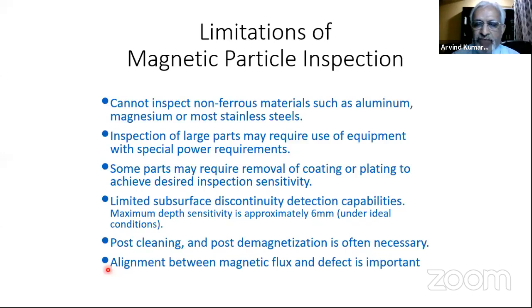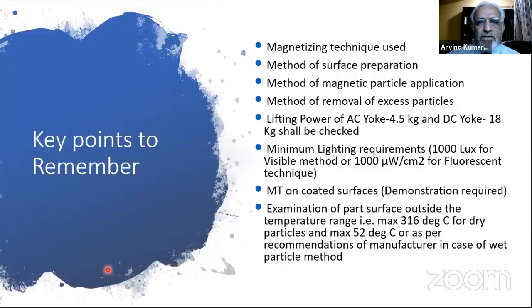Alignment between the magnetic flux and the defect is important. That means how you magnetize: if you are looking for a transverse defect, then you have to introduce a longitudinal field and vice versa. Again, what important things are there in this? What is my magnetizing technique? How do I prepare my surface? These are all essential things which we should follow. And once we have established them, we follow the same technique.